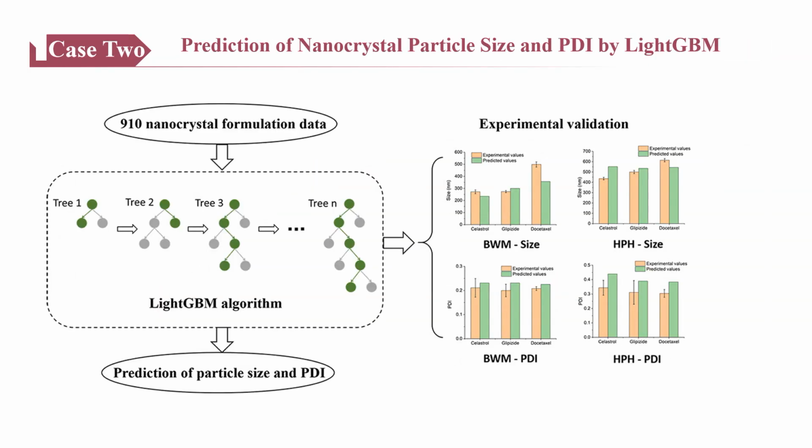Case 2, LightGBM for predicting nanocrystal particle size and PDI based on 910 sets of nanocrystal preparation data. A predictive model was constructed using the LightGBM algorithm, successfully achieving accurate prediction of nanocrystal particle size and polydispersity index, PDI, under different preparation processes. Experimental validation results show that the predictions are highly consistent with experimental values, significantly reducing the experimental workload of process optimization.